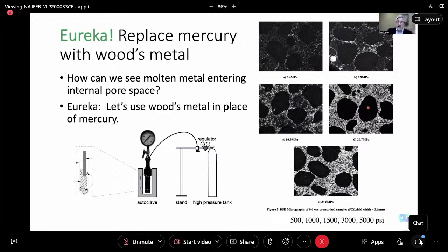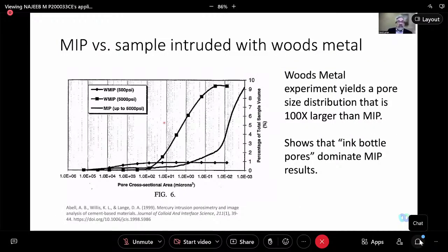and largely causes you to wonder about this because the results of the volume and the area that you see from the Wood's metal experiment from the MIP don't match, and they don't match because there's something called ink bottle pores. The pictures that we are taking with Wood's metal revealed a different story than the measurement of volume from the exterior of the sample. And it basically, in some regards, maybe makes you wonder why you would want to do a mercury intrusion test. It's not a really very good way to measure sizes of pores.